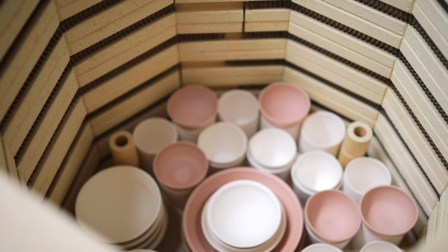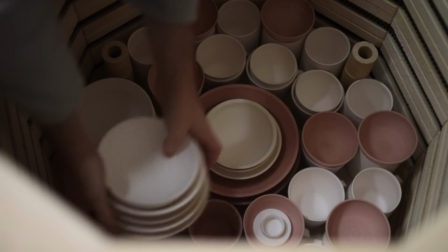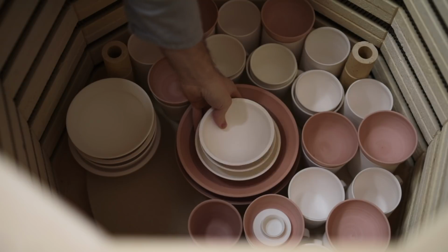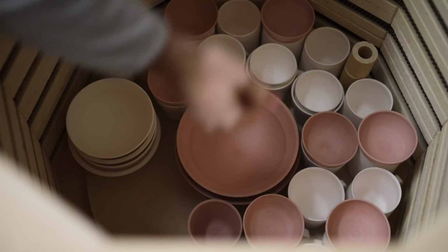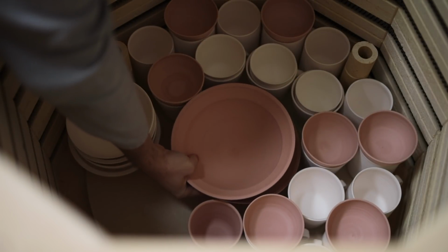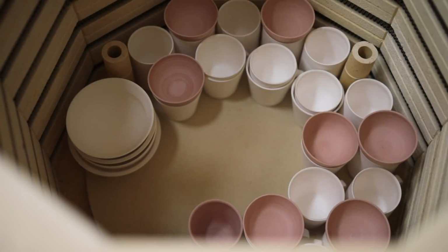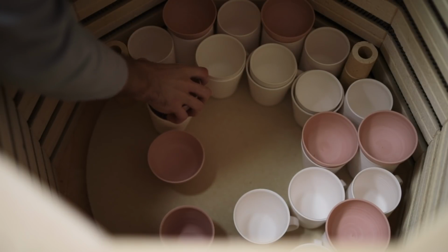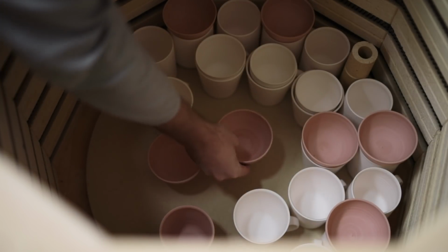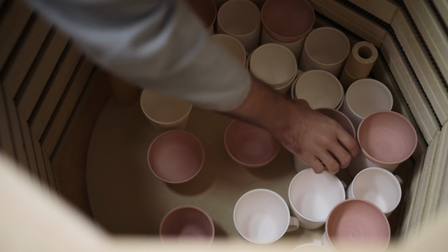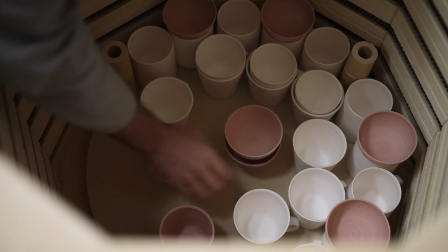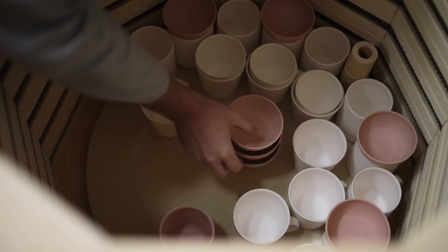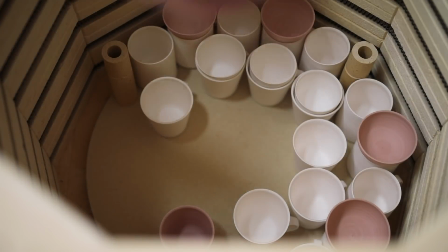And all this is the process of brushing on some wax emulsion onto the base of the pot, which essentially acts just like a wax resist and prevents glaze from adhering onto the bases of pots. If, during the final firing, I left glaze coating the bottom of my vessels, they'd solidly fuse to the kiln shelf as the glaze fluxes and welds to it, and thus the pot is destroyed, but there's also a high chance that the kiln shelf itself will be damaged.